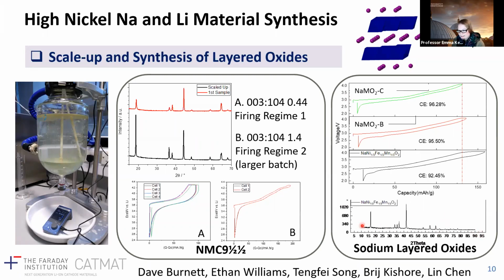And this XRD pattern here shows you that in this particular system, which is just a third nickel iron manganese, made by one of our PhD students, Tengfei, you can see that actually we need to do a little more to increase the ratio of the 003 to the 104 peak. And this has been improved up here with some 96% coulombic efficiency compared to the 92.